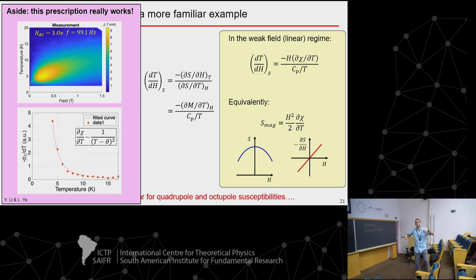If the susceptibility follows Curie-Weiss behavior, dχ/dT is 1 over (T minus theta) squared, and that's what you observe. It's a foolish way to measure susceptibility, because we've got other ways to do that. But this is just to say thermodynamics works, and we can do something similar for the cases where I can't measure the susceptibility by measuring the induced moment in the same way.